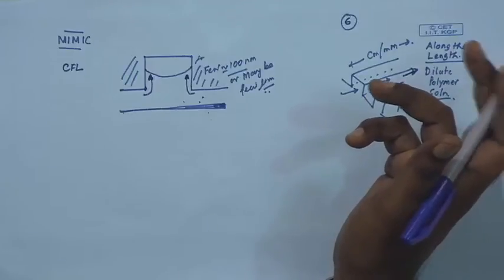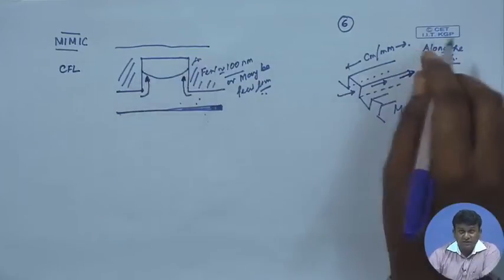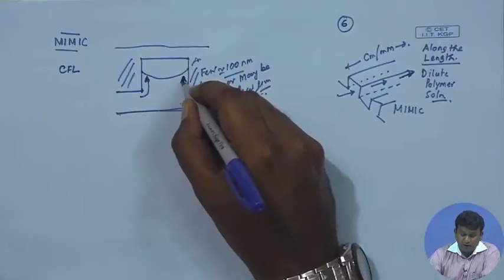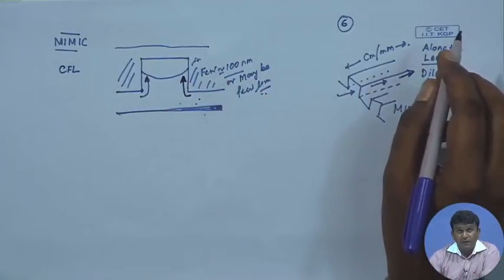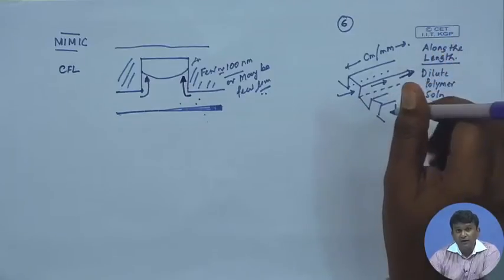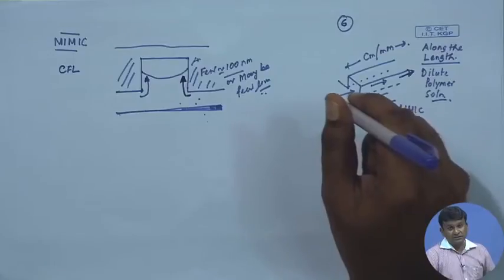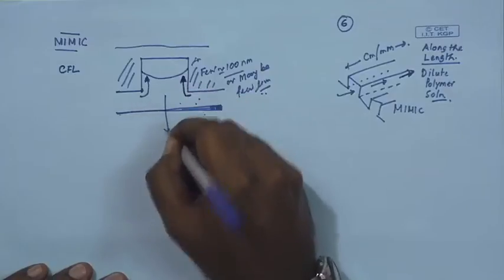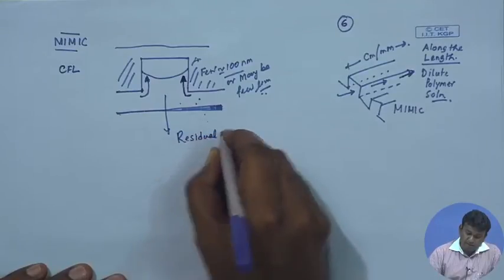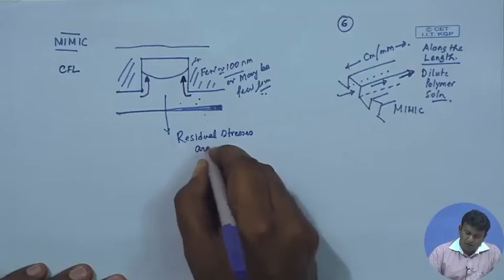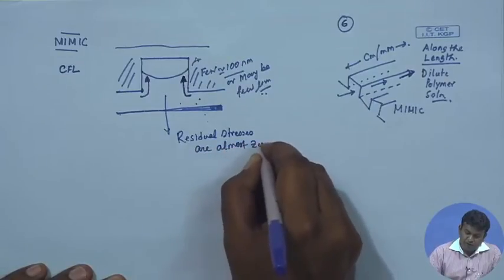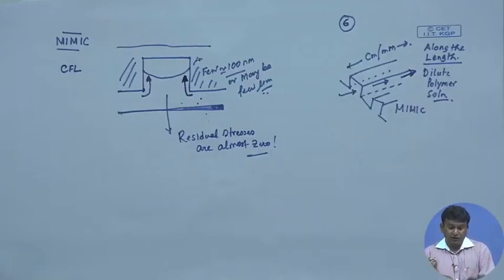What are the advantages? You do not apply pressure like NIL, you do not use a rigid stamp, therefore the issue associated with stamp removal is completely eliminated. You can simply peel off, because you are using a crosslinked Sylgard stamp. In the pattern replication dynamics, the meniscus rises along the stamp walls, unlike in nano imprint lithography, where the liquid adjacent to the stamp wall was actually going down. Therefore, the residual stresses are almost 0.